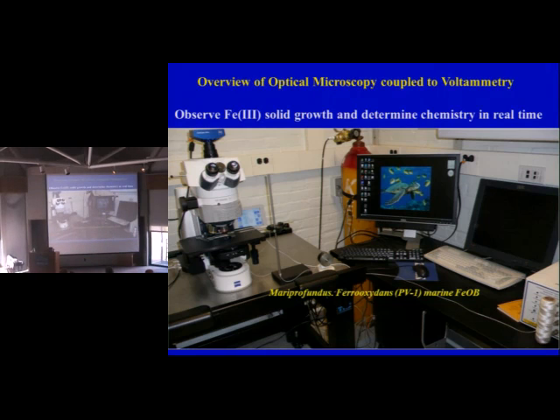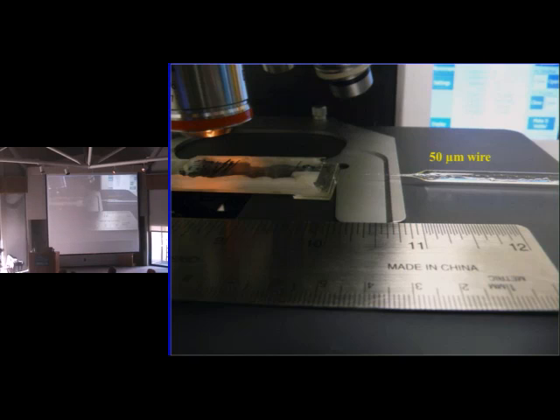So what I'd like to do is shift to the last section that I said I would do. I want to try to get done so we can have time for questions. Here's Clara's optical microscope. We're going to put on our electrode in here with a slide. And we're using the seawater strain that we have. Everything else that I showed you to date was freshwater. So we're going to switch gears and show you a seawater strain. And this is what it looks like. This is a 50-micron gold wire going down here, sanded and polished and plated, as we said before. And then there's your optics.